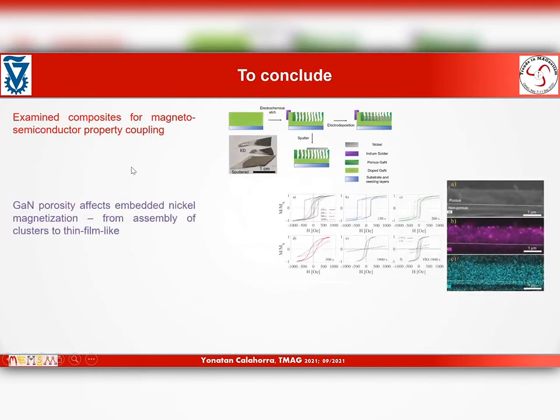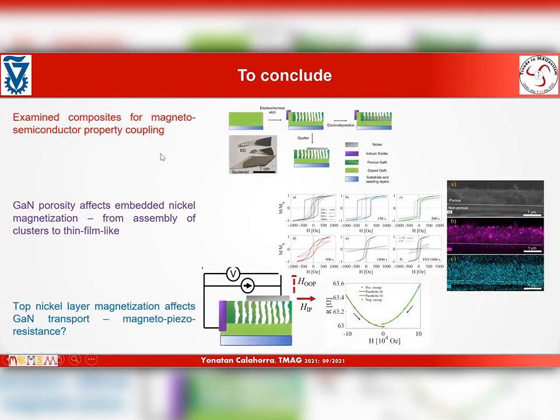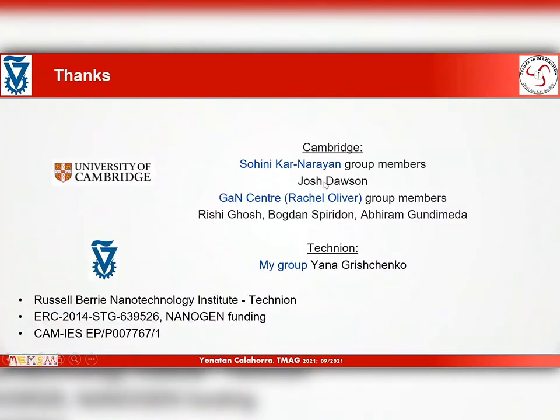So to conclude, we examined two types of composites of nickel and porous gallium nitride. We've seen how gallium nitride porosity affects the magnetization and the deposition of the layer. And we also saw some evidence of the magnetization effect on gallium nitride transport. So that's some interesting magnetic semiconducting coupling.